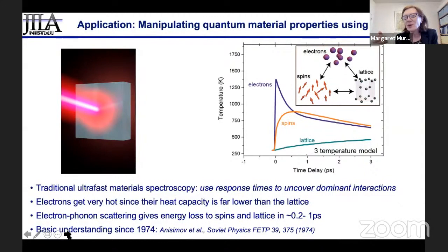So what we all learned back then was that the heat capacity of the electron bath in a metal is much lower than that of the lattice. So when you shine light on a material, the electrons are excited to very high temperatures, can be well above the melting temperature, but it's fine because the lattice heats up much more slowly due to electron-phonon collisions. And the spin system was also thought to heat up quite slowly.